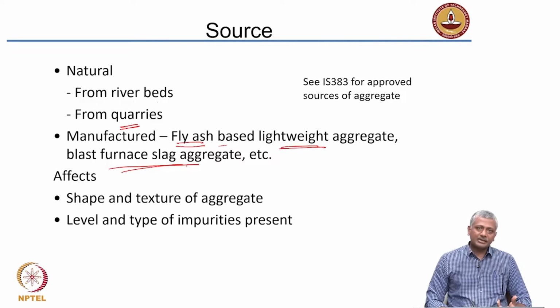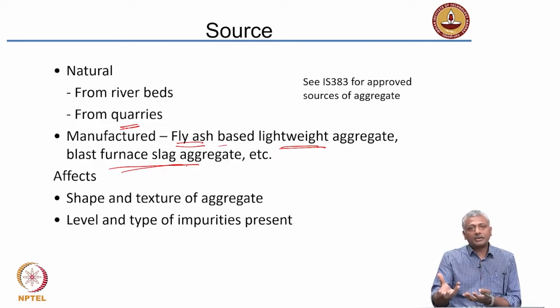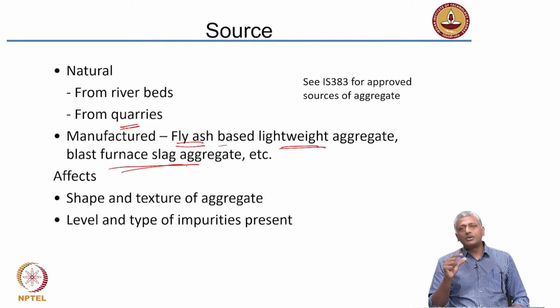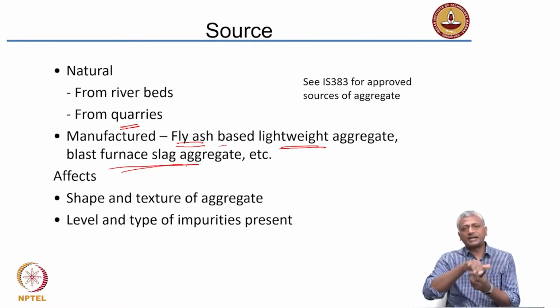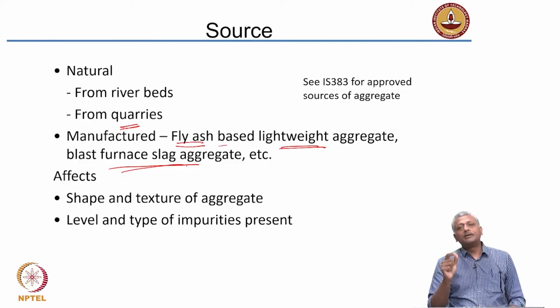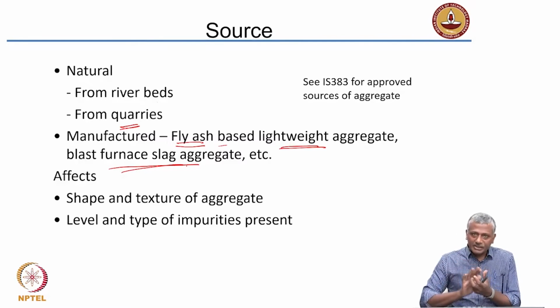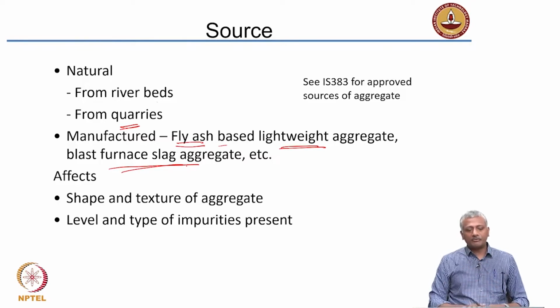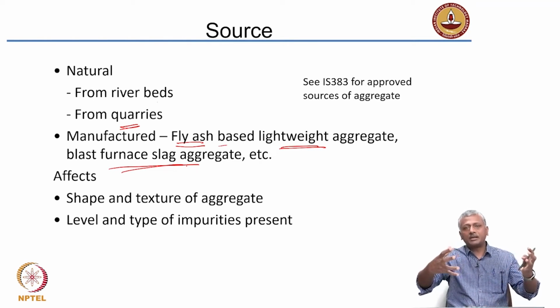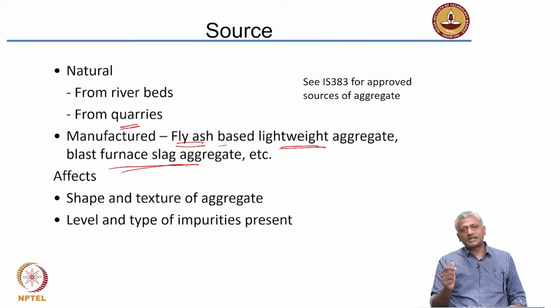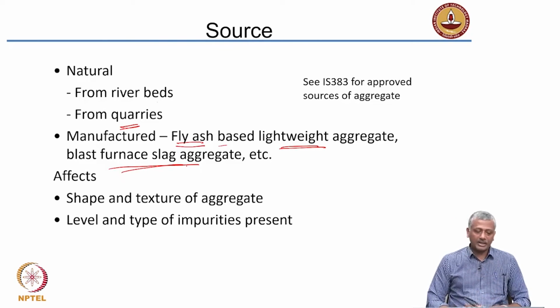And what happens as a result of these sources? One is it affects the shape and texture. As you can rightly imagine, when you have a flowing water above the aggregate, the aggregate that you get from riverbeds will have a nice and rounded shape, because the weathering because of the water has completely rounded the material, right. And secondly, because of this constant action of the water, the surface texture also will be very smooth. In a quarried aggregate, you are basically breaking large blocks of rock and crushing it into smaller sizes, so you get angular aggregate, and generally these angular aggregates will have a rougher texture. Okay. So, that will affect the properties of concrete. We will talk about how that happens later.